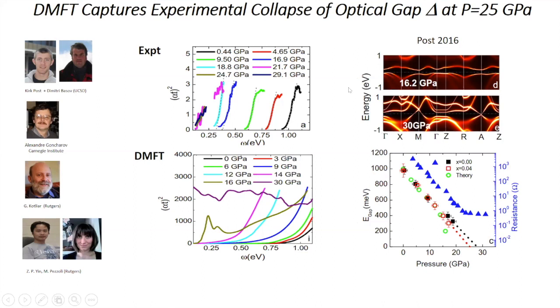Here would be the electronic structure calculations below and above the gap and the pressure where the gap disappears, and you can see that is faithfully reproduced in these calculations. Finally, these are DMFT calculations of the same thing as was measured experimentally. The colors are the same top and bottom for the different pressures, and you can see that the gap marches down consistently as a function of pressure and disappears somewhere between this pink and green values. The green value is 16 GPa, so that's pretty close to the critical pressure.